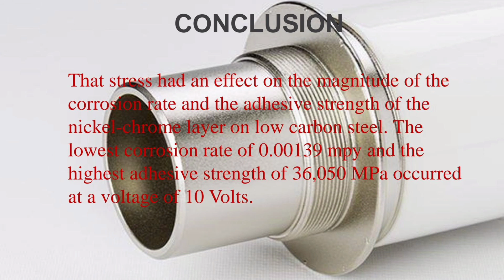Conclusion: stress had an effect on the magnitude of the corrosion rate and the adhesive strength of the nickel chrome layer on low carbon steel. The lowest corrosion rate of 0.00139 mpy and the highest adhesive strength of 36.050 megapascal occur at a voltage of 10 volt.